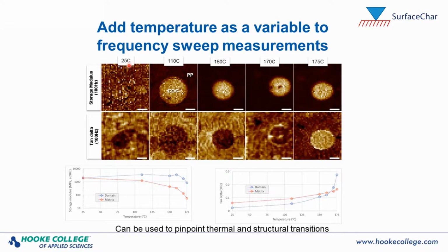You can also add temperature as a variable to these frequency sweep measurements. So here what we have is a blend of 2 materials with polypropylene in the background and a domain of cyclic olefin copolymer in the middle. And here what we're showing is the storage modulus as a function of temperature from 25 degrees to 175 degrees, and then the loss tangent from 25 degrees to 175 degrees. And we're just sitting in the same area, and now we're imaging this particular material as a function of temperature to see how these moduli change.